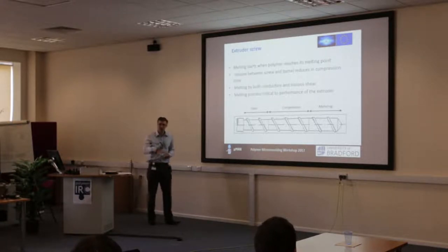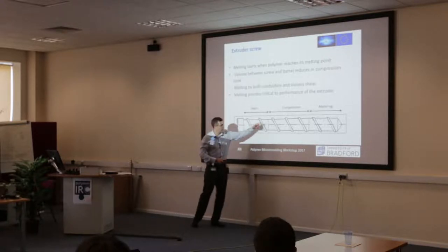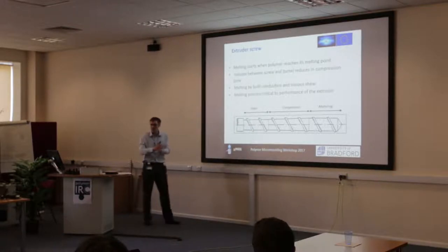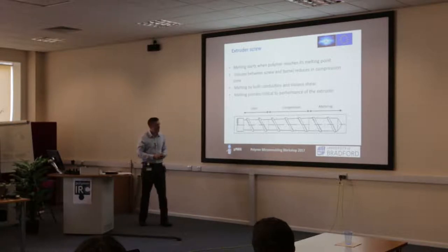And we also get viscous shear, because the screw is rotating, the polymer is being smeared around in these gaps between the flights, and we get a mechanical shearing action, which, because of the viscosity of the polymer, acts to heat it up as well.